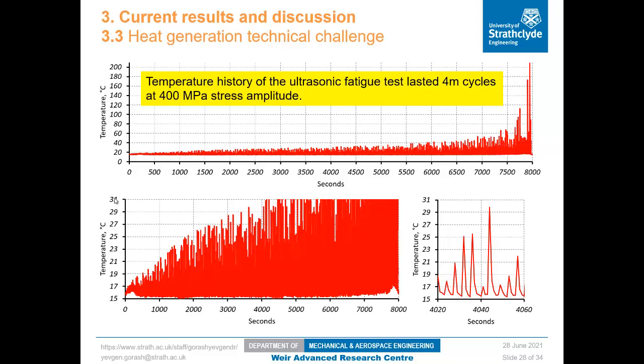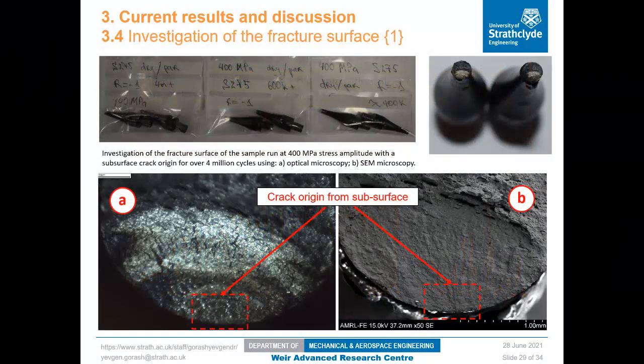With this kind of regimen, it was possible to keep the temperature in the room temperature range for half of the sample life, but then the temperature exceeded 30 degrees and also peaked to over 200 degrees just before failure. It is also worth mentioning that the fracture surfaces of the failed samples were investigated visually and using two types of microscopy: optical microscopy and scanning electron microscopy. With the help of these methods, it was possible to find the origin of cracks.